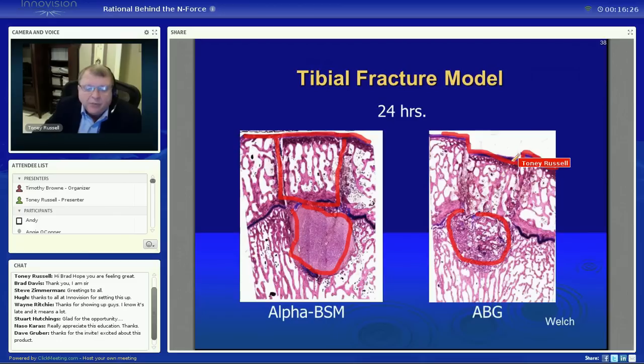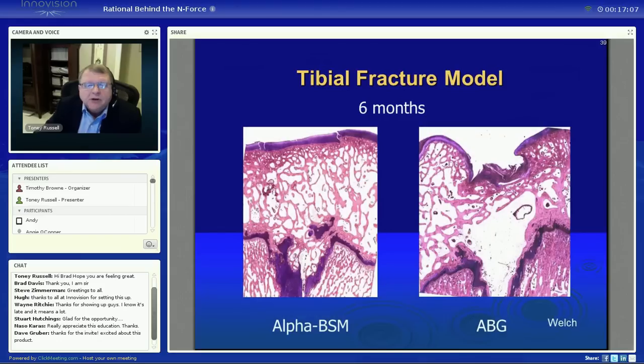Now, your doctor is going to say, no, that can't happen. Well, here it is. This is proof. And what happens is that bone graft they put in there compressed down further, just like potato chips. And if you step back and look at this picture, this little lacy network, this is the trabecular pattern. And when you have fractures that break this up, this trabecular pattern has to be regenerated. And just packing in chips doesn't give you the structural strength that you need. So the ceramic cement has much better compressive strength, and so it'll hold up to this load.